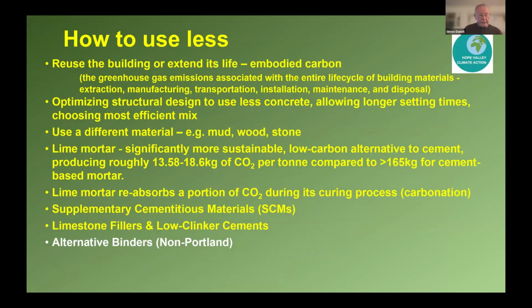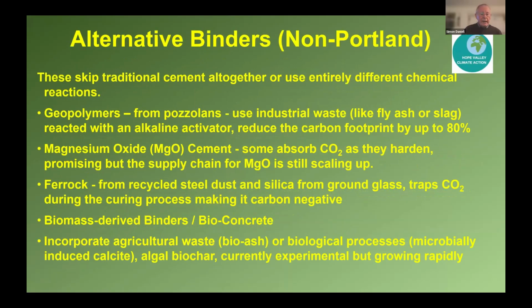We can use alternate binders. As you remember, I said that cement is the binder that binds the stuff together to make the concrete. We can use other binders which are not cement. And again, this is a busy slide, but just to pick out some of the things, there are geopolymers which come from pozzolans, but they aren't pozzolans as such. And these you treat with an alkaline activator, and that can reduce the carbon footprint. There's magnesium oxide which could be used. The advantage there is some of these absorb carbon dioxide as they harden, but there's a supply chain issue there.